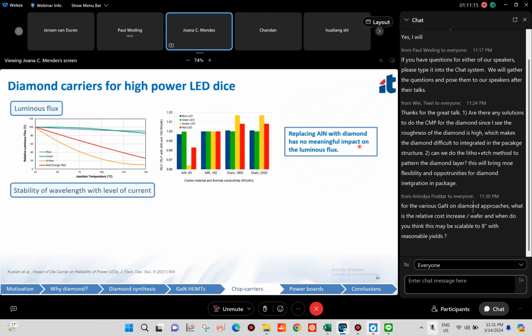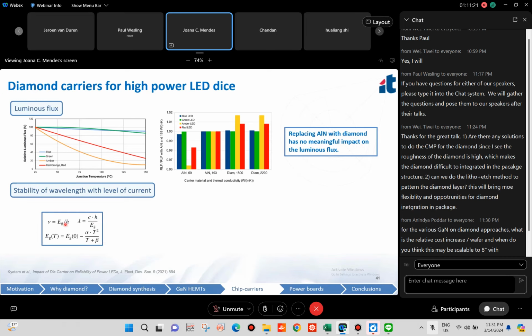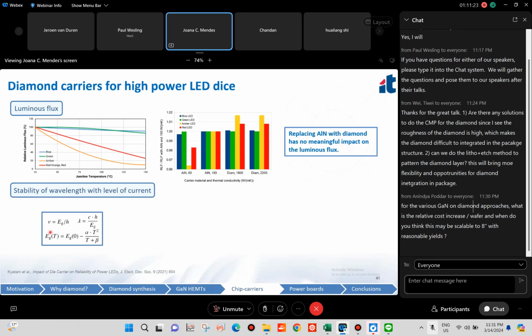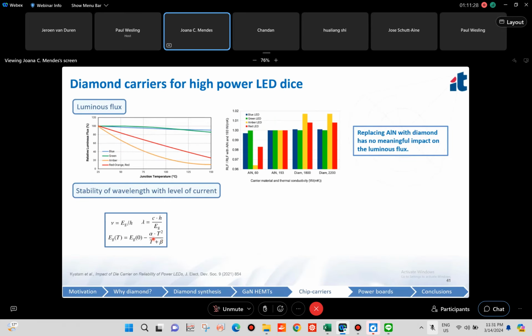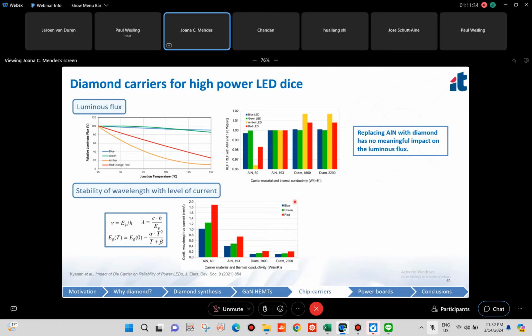And then we evaluated the stability of the wavelength with the current level. And here we calculated first, we estimated the band gap as a function of temperature, again, taking these parameters alpha and beta from literature. And then from here, we estimated the wavelength. And we've done this for three LEDs: blue, green, and red.